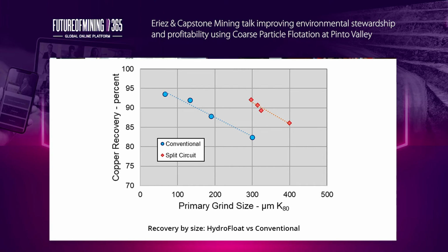The red diamonds show how that relationship can be pushed out with the HydroFloat so that the same flotation performance can be achieved at approximately twice the particle size. This means less grinding and a significantly coarser tail while achieving the same recovery. Considering about 30% of all of the energy used in mining is for crushing and grinding, this can lead to a significant reduction in electrical energy requirements. Additional energy savings can also be realized by having a coarser tail because there's lower dewatering and pumping costs.